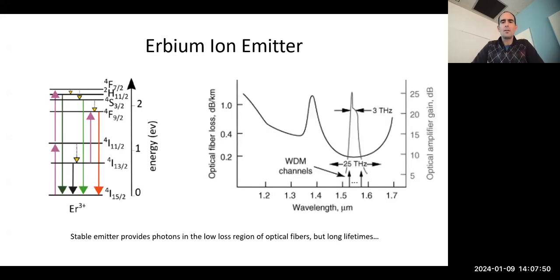Okay, so we are interested in erbium ion emitters, and like some of the defects in silicon emitters, one of the interesting features of these emitters is that they emit in the low loss region of the optical fiber spectrum. So optical fibers are particularly good for transmitting photons in the near infrared region, particularly around 1.5 microns. And you want to use this region because your single photons are precious. You don't want to lose them to losses or scattering. So working in this region is kind of key if you're going to do any sort of single photon or photon number state types of computational or communication schemes.